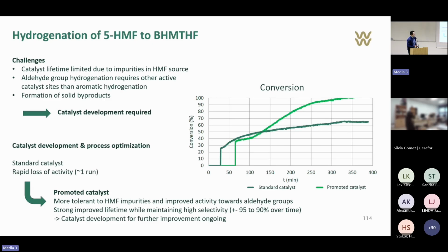But we developed a promoted catalyst, which is much more tolerant to the HMF impurities. And it also has an improved activity towards these aldehyde groups. And in this case, for instance, we were able to get a full conversion for one run.